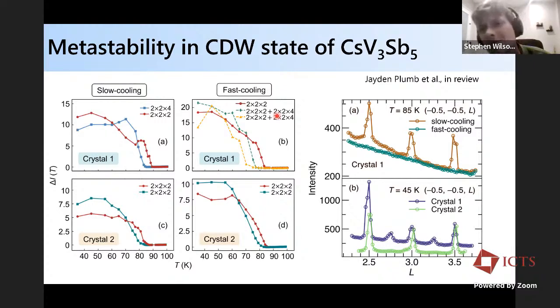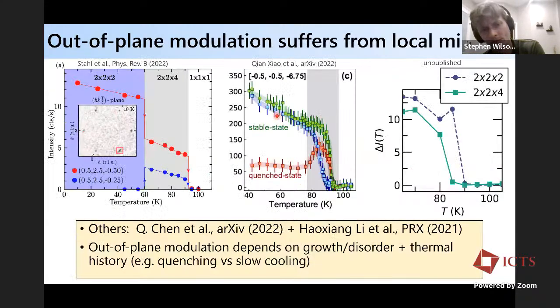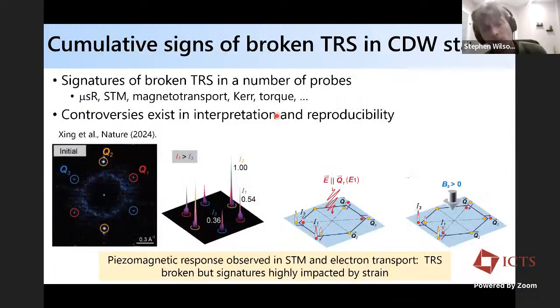Yeah. So I had actually a couple of questions. At the very beginning, you showed this STM measurement where you had the Fourier transform, and this was reproducing some earlier data, I think, from Hassan, where the pattern has been interpreted in terms of a chirality associated with the charge density wave. I had two questions here. One is, am I right to associate the peaks in the Fourier transforms with basically a structure factor, the same type of structure factor that you would measure in X-ray scattering, or is that not correct? That's one question.